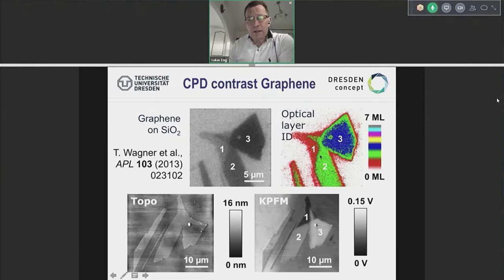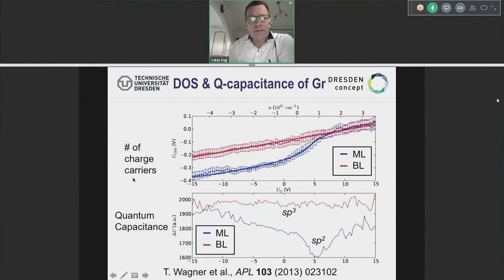But there's more to say. Tino Wagner found out a couple of years back that you can also say that these layers are changing in the so-called quantum capacitance, which is actually the density of states per unit cell and also per volume. Or in other words, this quantum capacitance, which is the second derivative of this Kelvin, lets you differentiate even between different hybridization, like SP3, which is a two-layer stuff, and then SP2 hybridization at a certain bias voltage. But this is something that has not been repeated by anybody, not on any other materials like molybdenum disulfide and things like that. So there's plenty of room open to the future.